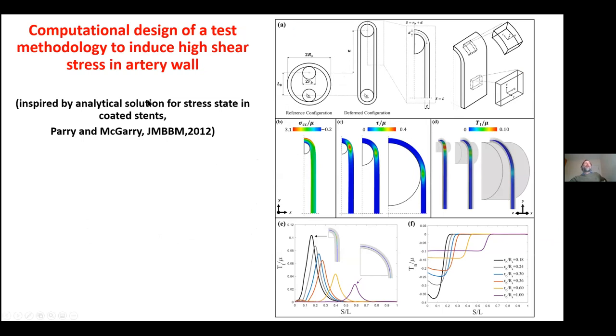So I had many years ago developed analytical solutions for the stress on a stent coating. And basically, in a stent, you have an arch region and a straight strut region. And we found in this analytical analysis of this kind of a structure that we get very high shears at the interface between a circular arch and a straight region. So we decided to try and apply this to the artery. So we cut a ring of artery like this, and attach it to two loading bars and stretch it like this, make it stretch from this circular configuration to this configuration.